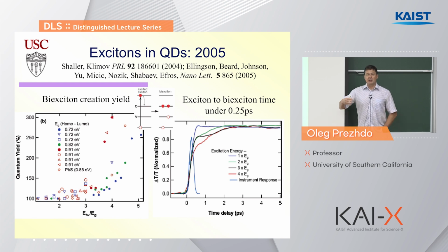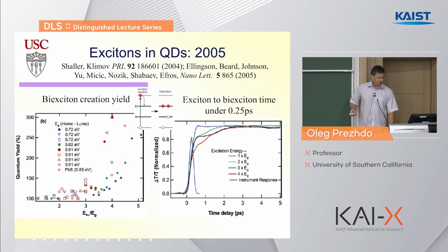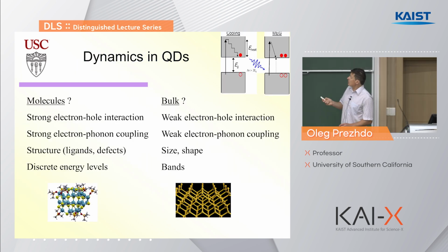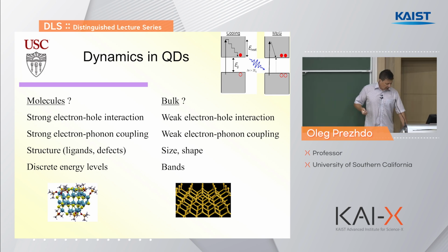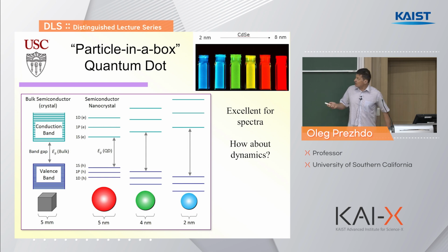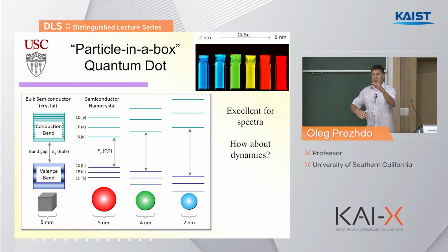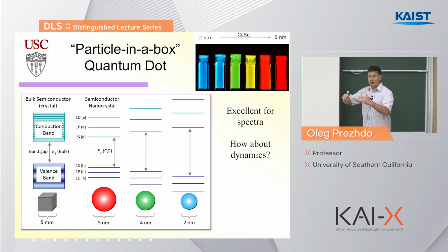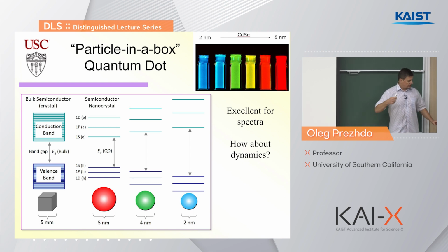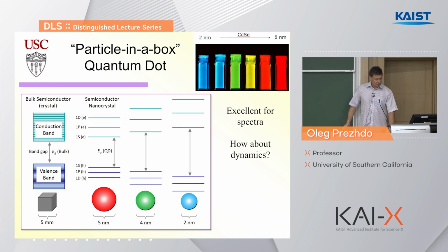And this motivates actually the methodologies we develop and the kind of studies that we do, time-resolved experiments that can study such very fast processes. So what was interesting is that, remember the logic was that relaxation is going to be slow. So instead of relaxing like this, losing energy to heat, you can do something useful. And the argument was that if you make your dot smaller and smaller, you're going to open up gaps, going to be larger and larger. And therefore, this relaxation, energy loss to heat, should be slowed down in smaller dots. And therefore, you can do something more useful than just losses of energy to heat.